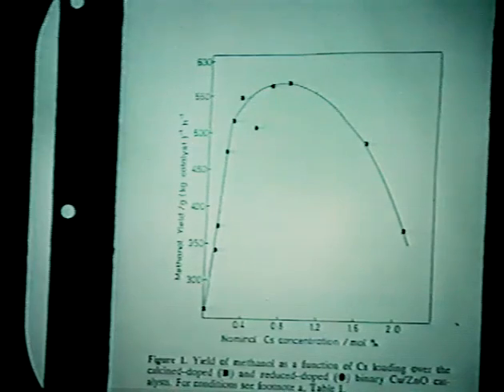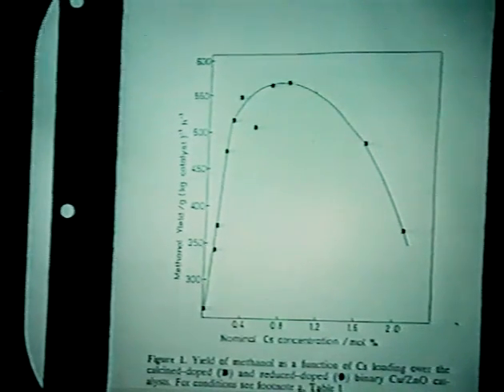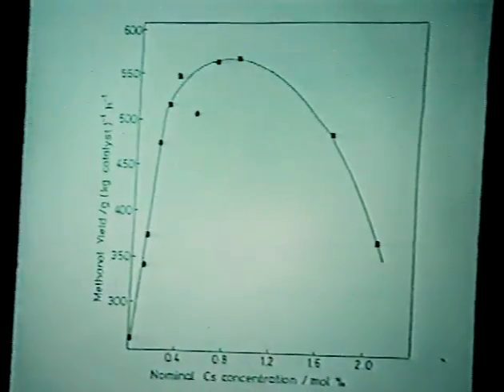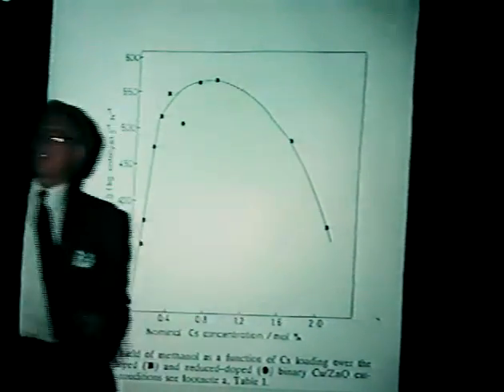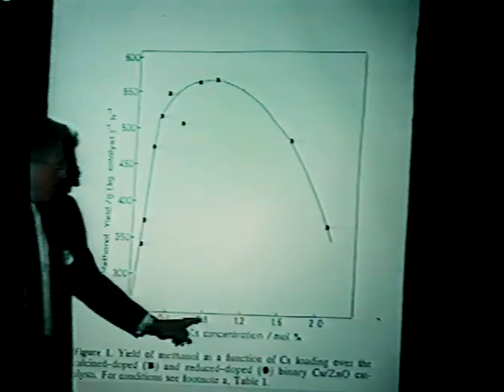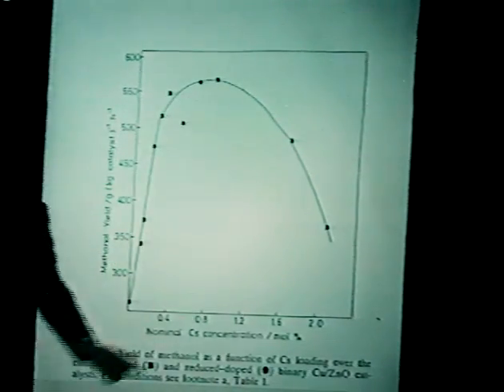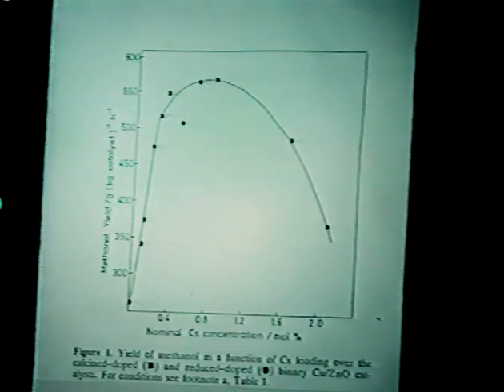Now, I must mention that this alkali doped catalyst is still under the methanol synthesis conditions, highly selective for methanol, even though you might have 1 or 2% of cesium in it. Incidentally, this is a nominal concentration. We know what the surface concentrations are. We know that the cesium spreads, and we know that it sits primarily on the zinc oxide phase from various surface analytical researches. At this point, the surface concentration of the cesium is about 20% of the surface is covered with the cesium salt, 80% is still the hydrogenation component. You need 20% of base and 80% of hydrogenation component to make that catalyst work at optimum.